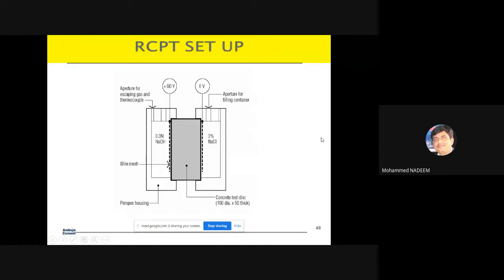RCPT is a very simple setup. I will not explain in detail, but the concrete is exposed to sodium hydroxide on one side and sodium chloride solution on the other side, and then a 60 volt current is passed. Naturally, it is nothing but a cell setup where the ions get pushed from one surface to another, which is measured in the form of charge, given in coulombs. Coulombs are how much charge is passed through the concrete. High charge passing means your concrete is more permeable. Low charge passing means your concrete has low permeability. So nowadays people are looking for permeability in terms of RCPT less than 1000 coulombs in the majority of structures.